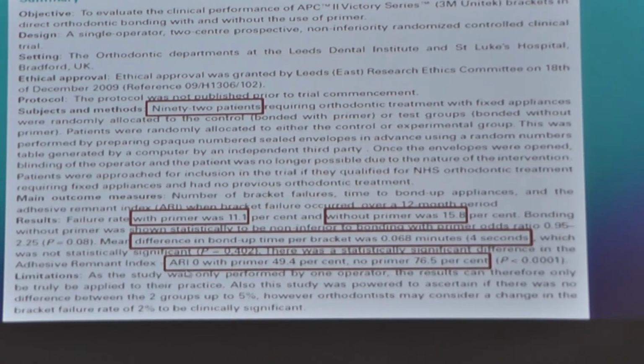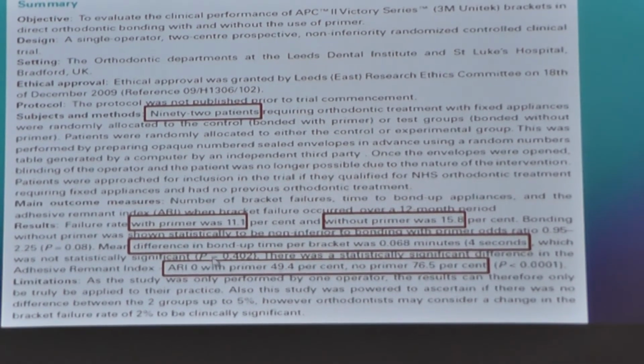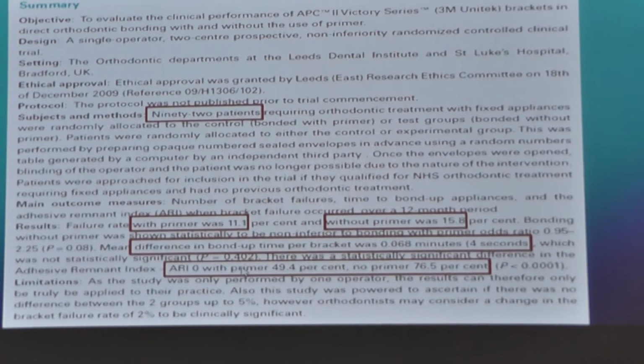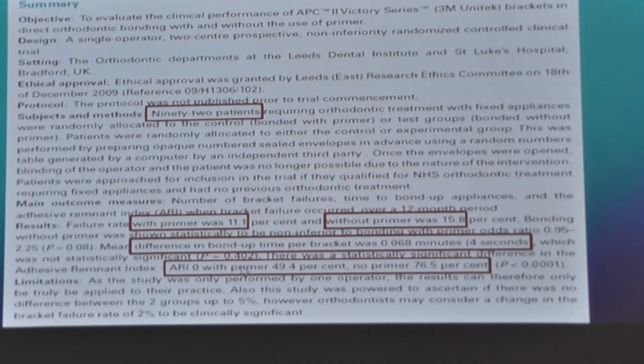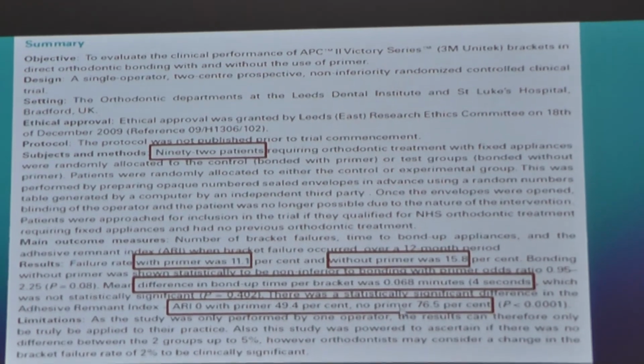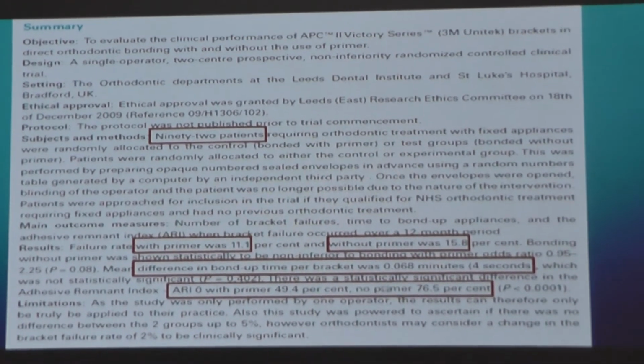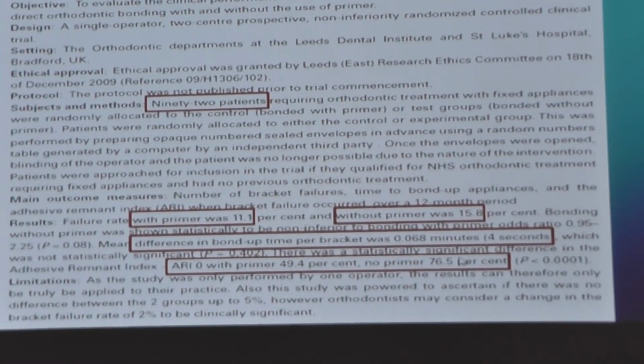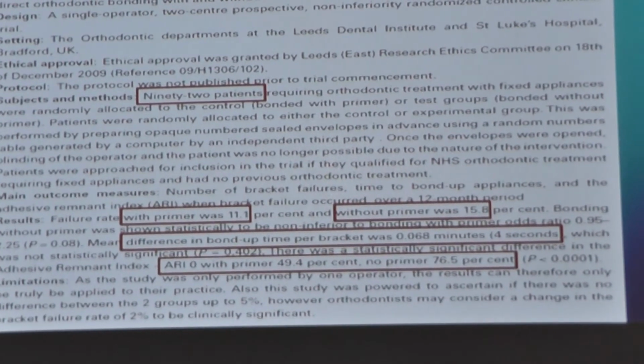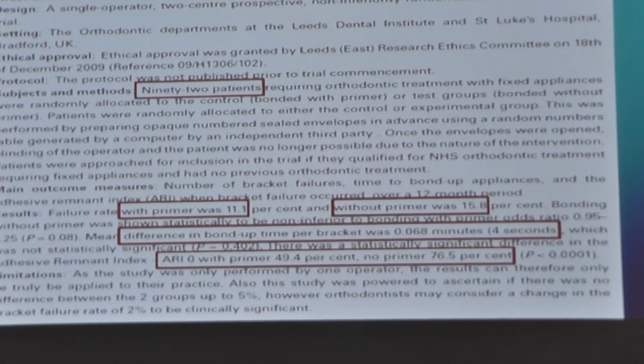And yes, it was also shown that when primer was used, an ARI of 0, so no adhesive left on the tooth, was 50%, while it was much more common if no primer was used. So without primer there was a higher rate of clean, polished enamel surfaces upon bracket removal.